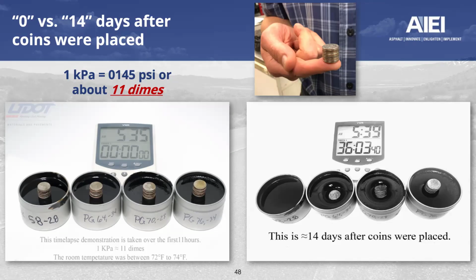They did time-lapse photography. We can see the initial photograph on the left and the final photograph after nearly 14 days on the right. And notice the differences between these materials. When we look at the far left material, that is a neat asphalt. It's a 58-28. We have progressively higher polymer loadings for the 64-34, the 70-28, and finally the highest polymer loading in the 76-34. And notice that after 14 days, the evidence of the dimes is at best minimal.